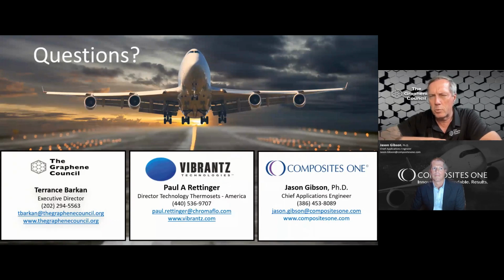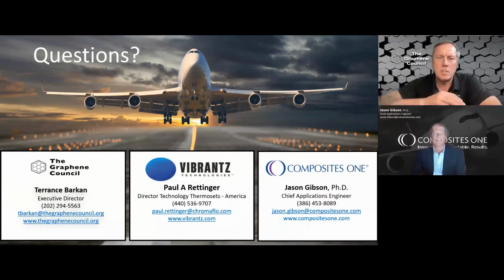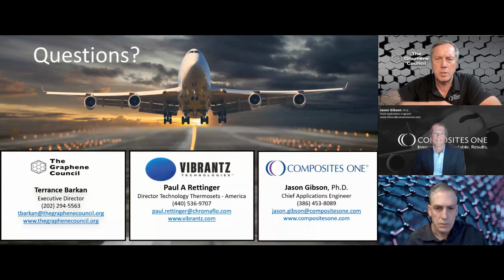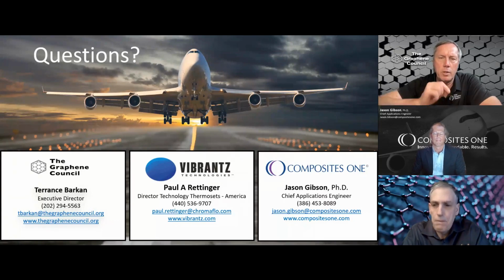Because I think there was a question here about surface area and rheology, and that does have a big impact. And I can't remember if it was just mentioned, but when the master batches were being formulated, some of them could be compounded to as much as a 20% weight of the graphene, and some were, the max you could get was about 2 or 3% because of viscosity issues. So there's a big range in how individual particles of graphene work.